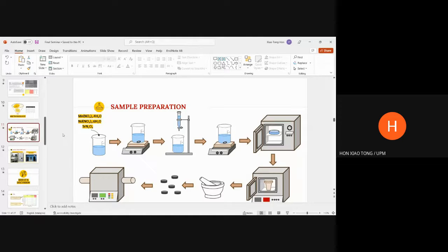Before I start my study, in our lab we already did some preliminary experiments. Based on the experience that my lab mates found, for thermal treatment and sol-gel method, the suitable temperature for calcination is around 500 degrees Celsius for 5 hours. It's the most optimum one for the calcination process. So that's why you choose the 5 hours, right? Yeah. Okay, thank you. Okay, thank you for your question.